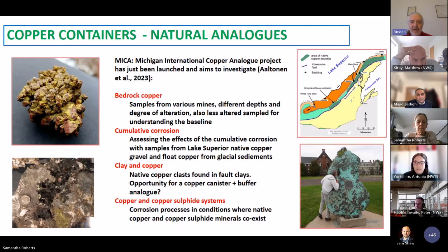Majid mentioned earlier that the interfaces are important, and they're hoping to assess how much transport, for example, of copper into the clay has occurred, and has that affected the clay properties in any way. And also, especially for organizations such as Posiva, there's copper and copper sulfide systems. So they've got some nice material there where they've got copper sulfide and native copper coexisting, and trying to understand why. So NWS is involved in this as well, along with NAGRA, NWMO, SKB, and BGE from Germany. So it's brand new. I had a good chat with Ismo about it. Looks nice. They have some wonderful material, and it looks as if it will run for a few years. So keep your eyes on that one.